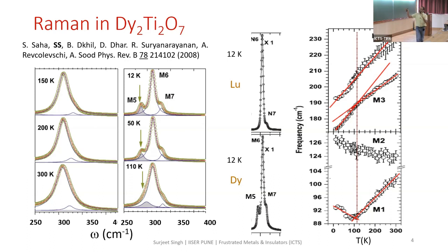But for understanding the data which I'm showing here, you don't really need to know what a spin ice is. In case you don't know, I'm talking to the students right now. So what do you see on your screen? You see the Raman spectra of this crystal, Dy2Ti2O7. And I'm showing you a very small spectral range, which extends from 250 wave number to about 400 wave number. All right. In the Raman spectra, from the group theoretic analysis, you expect 6 Raman active modes. So this is one of the modes, the most prominent modes at room temperature.